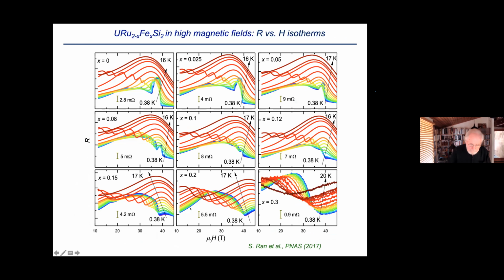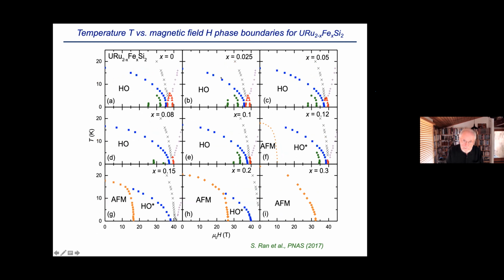Okay, now we've wanted to do this in the system we're working on by looking at various iron concentrations and then doing similar measurements. And so I know this is very complex, but basically these are our data like I showed you for the pure compound. And this is the pure compound here. And then these are successively larger amounts of iron. And so this is all in the hidden order regime here. And then over here, you get into the antiferromagnetic region. And then these are the features similar to what I showed you right here. But anyway, if you take these features and you pick out the relevant temperatures and fields, you can make it look a little bit more appealing because you now have basically phase boundaries.